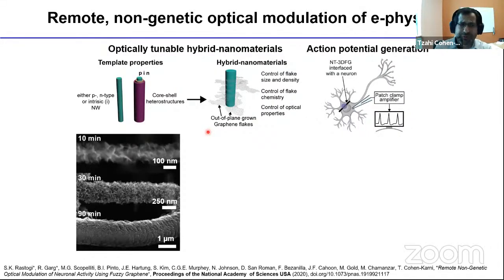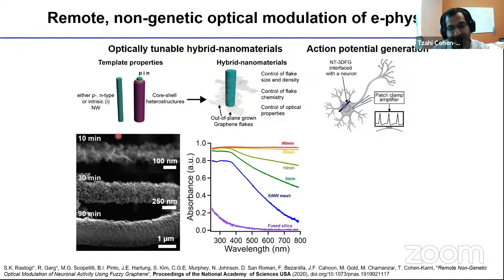These are the library of materials we generated. You can see that we can literally tailor the density of the flakes and the size. You can see that the scale bar is changing. And this is just by controlling the time of the synthesis. Again, it's a plasma-enhanced chemical vapor deposition process we are doing. You can control the density and size of flakes by controlling the temperature of the process as well. So we take one of these wires and actually, let me go back.